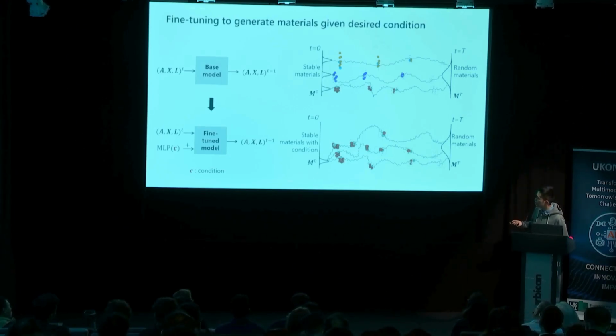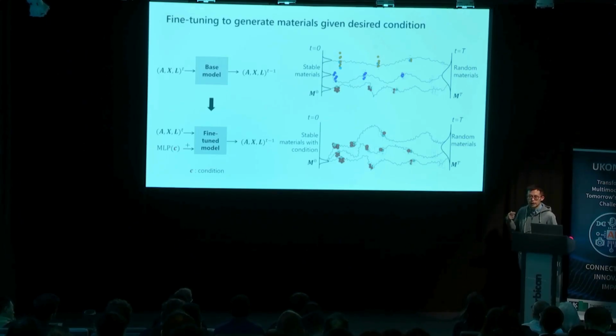The good thing here is that this condition can really be anything that you care about. So material scientists can just bring in their own data for the things that they care about. The second thing is that you don't need a huge data set here because it's just fine-tuning. We have tested down to as few as 5,000 data points. Now you can fine-tune a model that can generate materials based on the properties that you define.